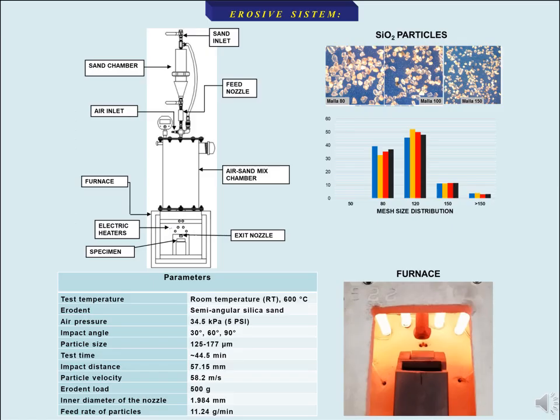For the erosive system, a sandblast type rig was used. In the upper part, the sand is poured. In the middle part, occurs the combination of the air and the erosive silica sand. And finally, at the lower part is the furnace chamber, where the sample is eroded at a high temperature. In the lower picture, the inner part of the furnace is shown. It can be seen the exit nozzle and the specimen holder in a high temperature atmosphere.